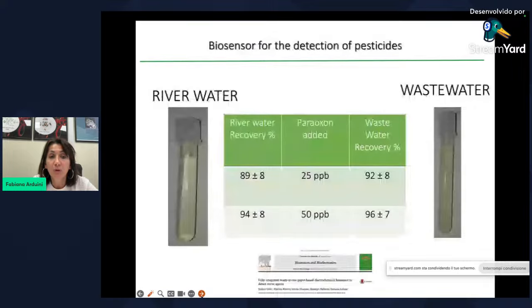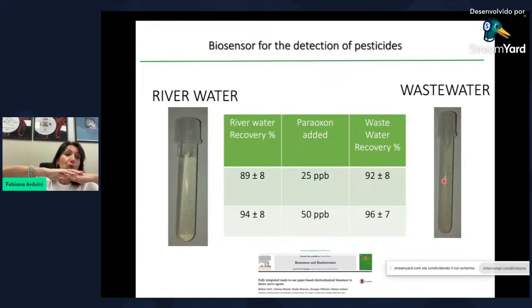So in this case, we also demonstrate the accuracy of the system using complex matrices like river water and wastewater, and we can see the particulate, but we didn't observe interference. If we preload the sample in the opposite site from where we print the electrode, we exploit the porosity of the paper to block the particulate, so we have no interference. So we use the porosity of the paper to treat the sample, to contain the reagents, and also for microfluidics, in this case in lateral flow configuration.